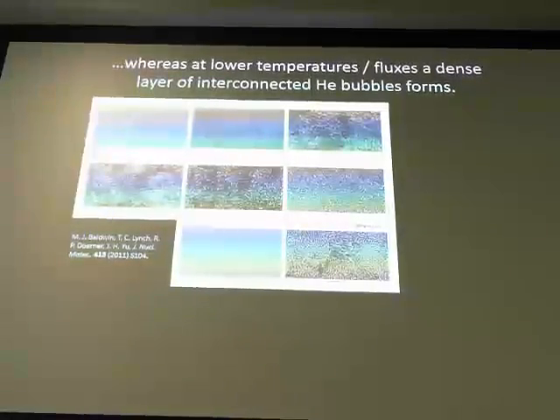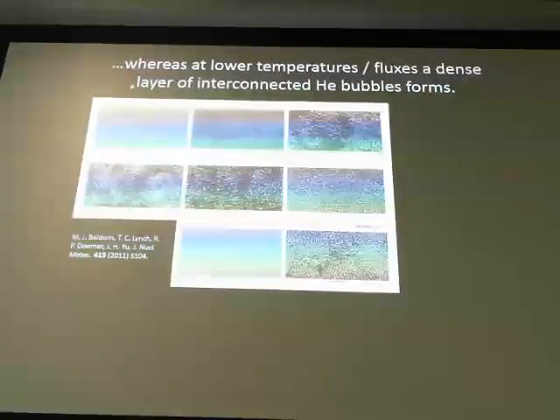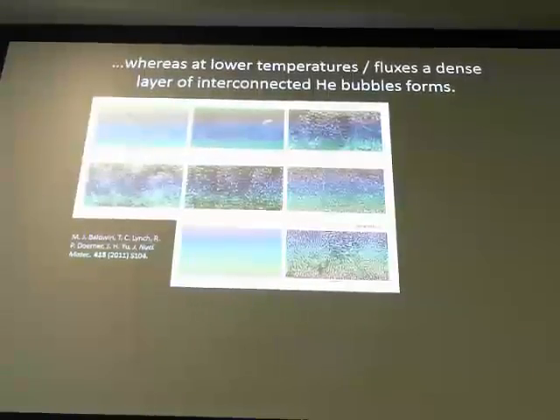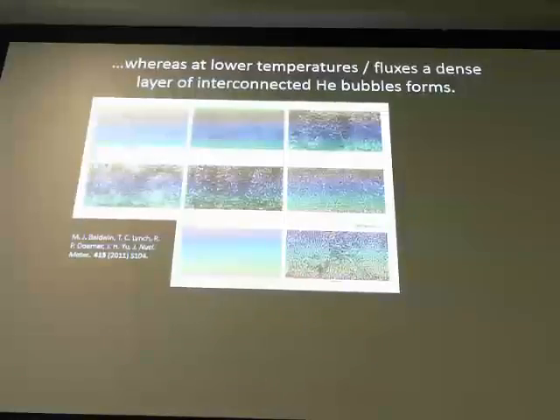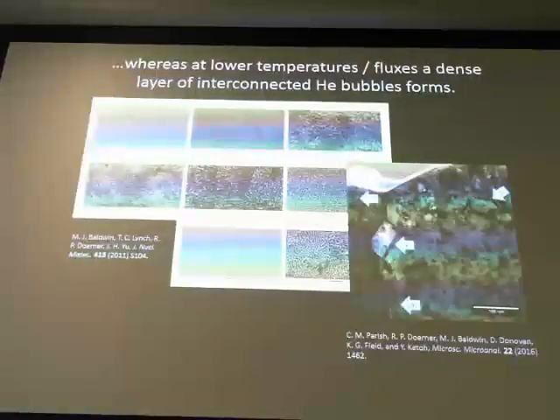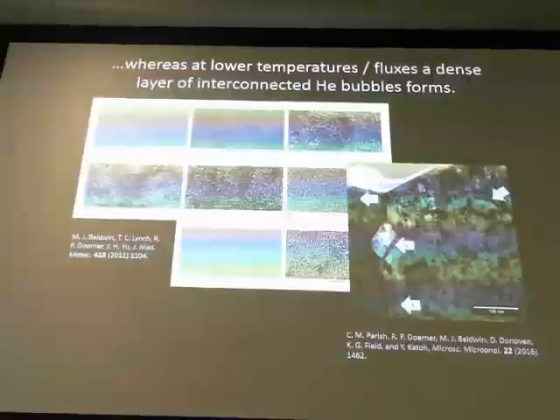So you can see that there's some energy dependence to this nucleation of the coral structure. These are relatively low energy, obtained in a helicon plasma device at different implantation energies, and they see some of the initial formation of this sort of coral structure. It seems to be a pretty strong threshold, only a 5 eV difference between the two cases, where it's almost completely absent versus where you see a pretty dramatic onset of this phenomenon. So there's been some effort to look at this, and also, at least in this case, to look at the formation of bubbles and voids in the near surface as a result of helium implantation.